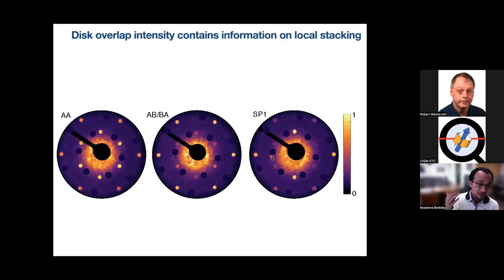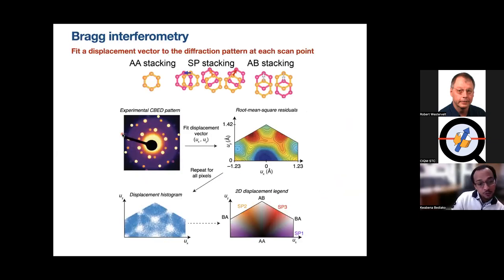And so the significance of this is that looking at the overlap regions, and those overlap regions comprise a significant portion of the entire signal because the twist angles are so low, you effectively get different diffraction patterns for different stackings, right? But just to emphasize that we're looking at the overlap region, if you look very closely, you do see the regions of the signal where the beams are not overlapping, and we don't use that. So we don't just, in a binary way, assign different stackings to a particular diffraction pattern.